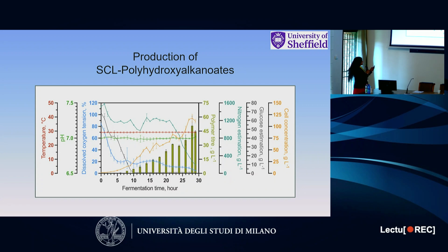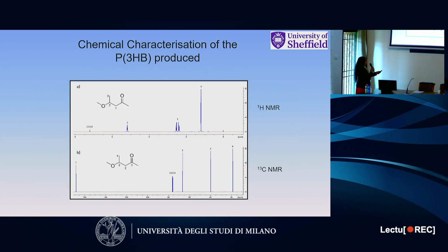So this is the type of conditions that I control: dissolved oxygen tension, pH, temperature, nitrogen concentration, every single thing is absolutely watertight, which ensures that every single time I produce the polymer, it has exactly the same molecular weight and monomer content. Extremely important for making things with these polymers.